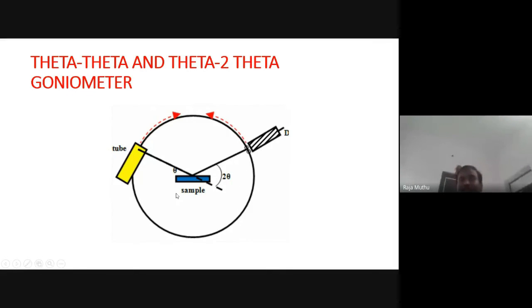We are much more interested in the study of XRD spectra, how to interpret it, which is more important than the physical components of the XRD instrument. There are theta-theta and theta-2theta goniometers. What is the theta-theta goniometer? In the theta-theta goniometer, the sample is fixed in the sample holder, whereas the tube and detector move in steps of theta. The tube and detector move with the same velocity theta. That's the theta-theta goniometer.